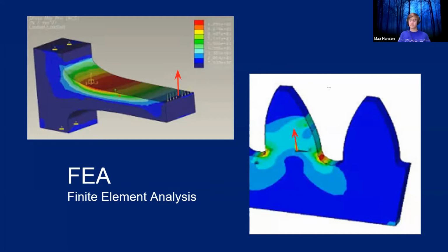And then on the left or right here, we see a gear tooth basically. And you can see that when the force is applied upward, that's where the gear tooth gets the most stress. And then you can maybe increase that fillet a little bit to make it even stronger. So you can see as he's circling, those are the areas of highest stress that are most prone to breakage and snappage.